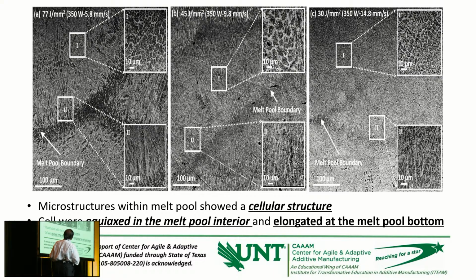This is one good example of how the grains evolve in the AM process material. This is the center of the melt pool. You get equiaxed grains, cellular structure basically, and at the bottom of the melt pool, you get mostly elongated grains because of the thermal gradient. If you go by the earlier R equal to V cos theta calculations, you will see that they are inclined in a certain direction compared to the laser motion and so on. So you can precisely predict the growth direction of these grains, and based on the G by R factor, you can predict whether they are elongated or equiaxed and so on.